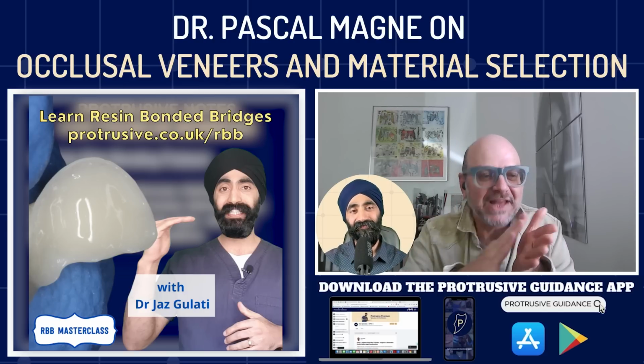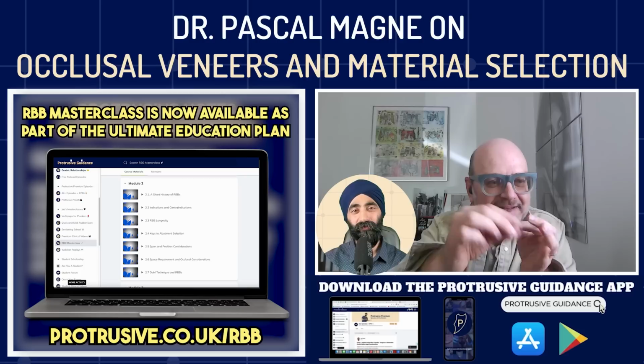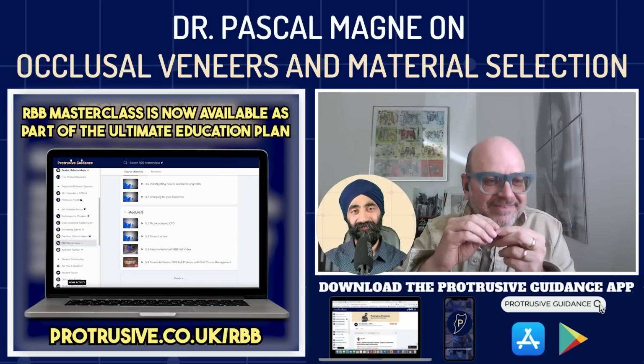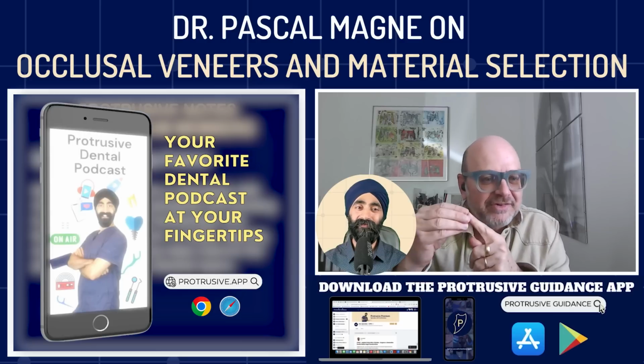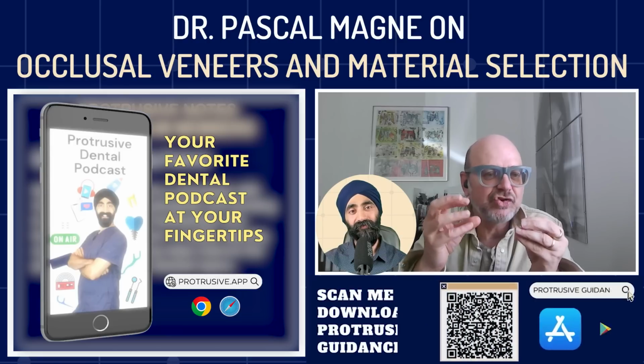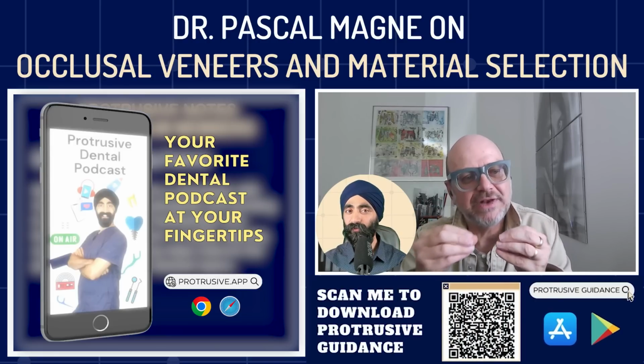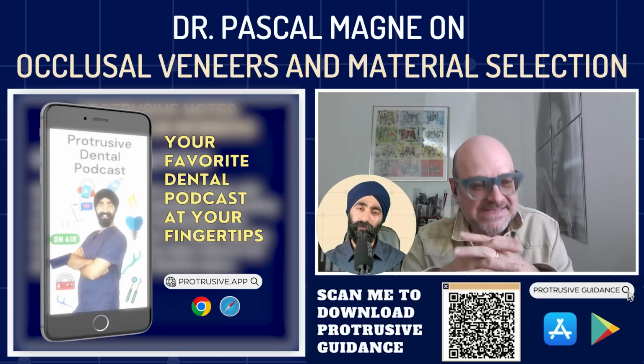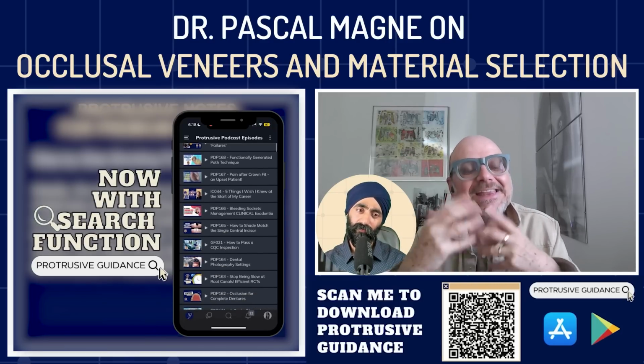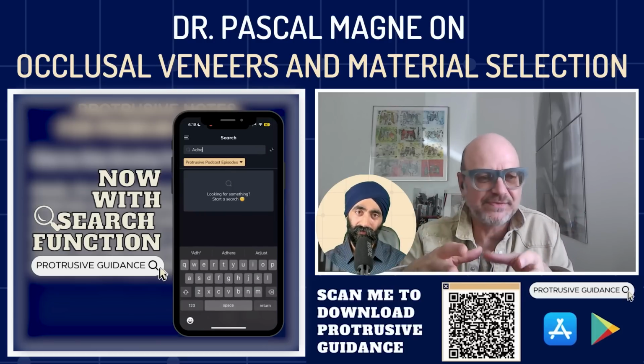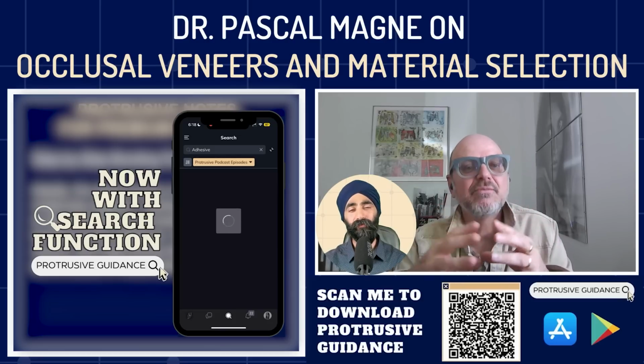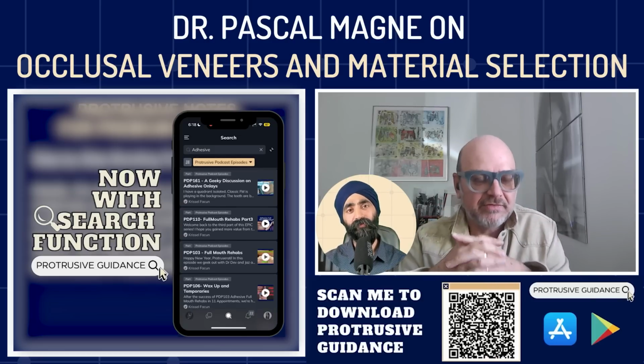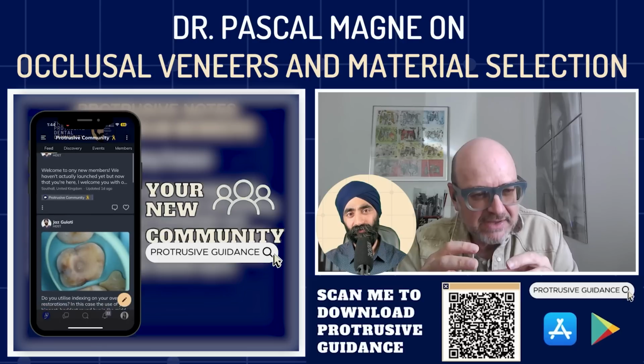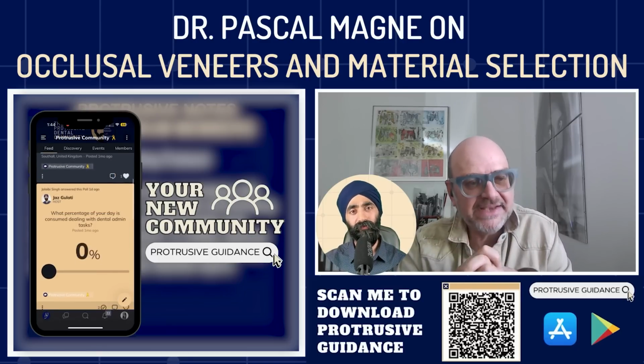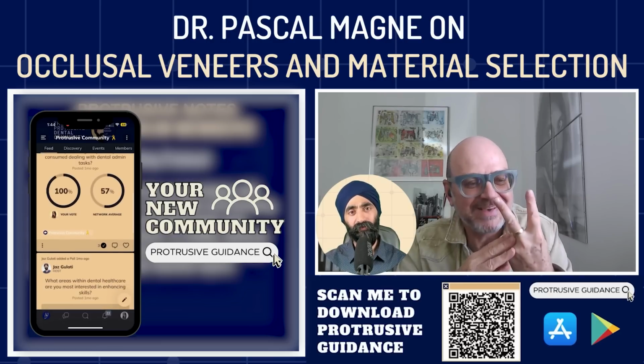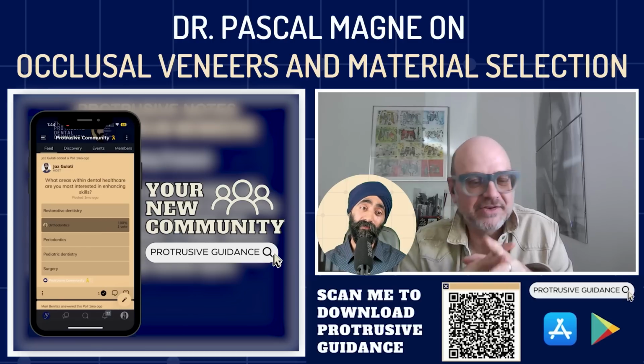You know, the silane, ideally you would like one monolayer, with each molecule aligned like a little soldier, with the hydrophilic part against the restoration, the hydrophobic part against the adhesive resin. But you have more than one molecule, they are stacking on each other. And the use of the heat will increase the cohesiveness between those layers of excess silane. But when you leave the silane in excess to dry by itself for 60 seconds, for instance, then you create a huge excess of silane. And then more excess means more problems with the cohesiveness of those layers. The good news is when you heat dry the silane, you increase the cohesiveness between those layers, you improve the performance of your silane by 2 times, according to an old study by my dear friend and colleague Jean-François Roulet.